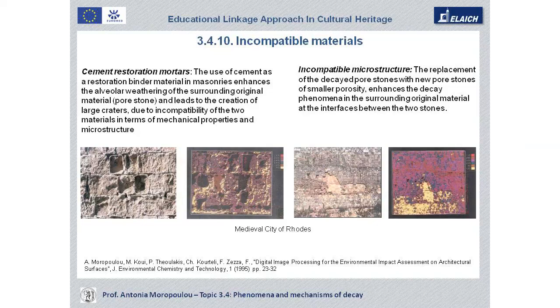This photo is digitally processed and gives the image of the very dense stone in yellow, and the original ones in coffee and Bordeaux colors, with blue and black as the points of accelerated corrosion. We may observe around the yellow surfaces blue and black, appearing very densely in relation to the original surface, meaning that we have acceleration of decay at the interface of new to old material.